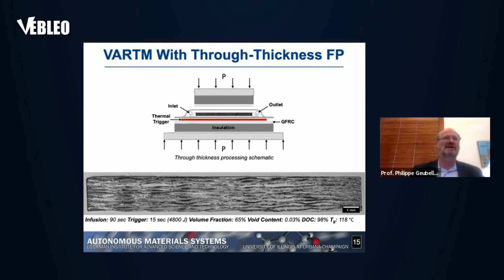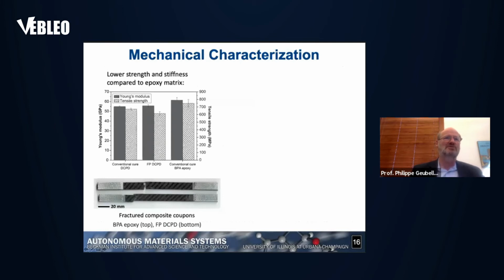Now, obviously, we want to emphasize the mechanical characterization of these. So we always compare the specimens that we manufacture using frontal polymerization, which are the middle bar, to those that we make using conventional cure, so using the manufacturer suggested cure process in an oven. And obviously, we also compare that with the traditional composite used in the aerospace industry, which is a carbon epoxy system. And so what we observe is that the properties, the darker bars correspond to the Young's modulus, the patterned ones correspond to the tensile strength. What we observe is the properties are relatively similar to those that we would obtain using a conventional process. They're not as good as what we would get with the carbon epoxy system.